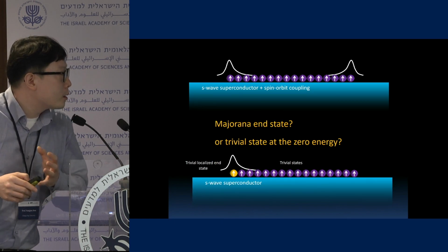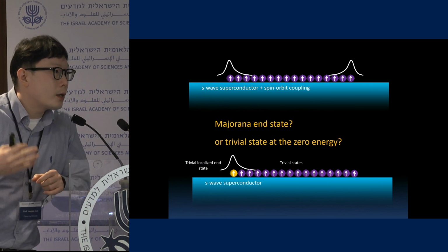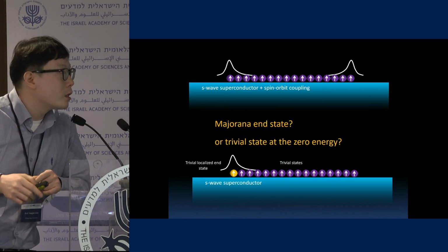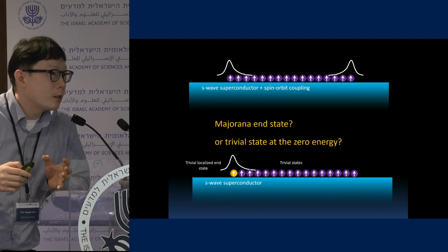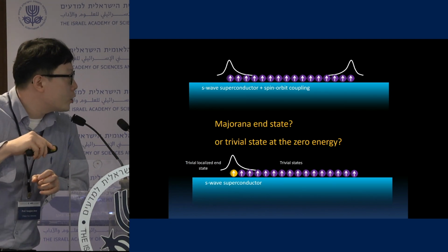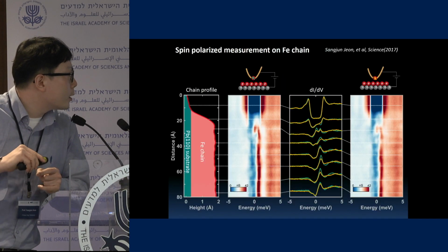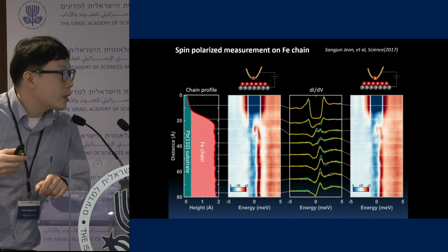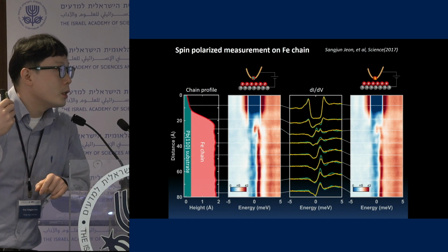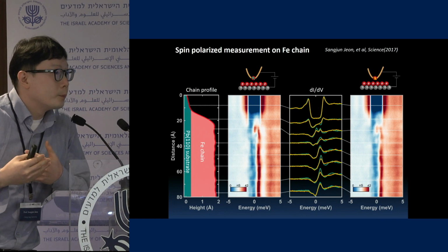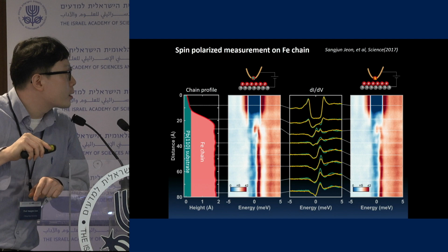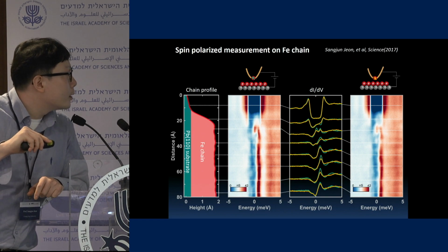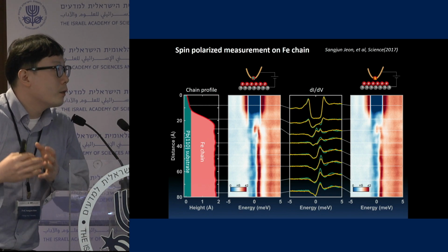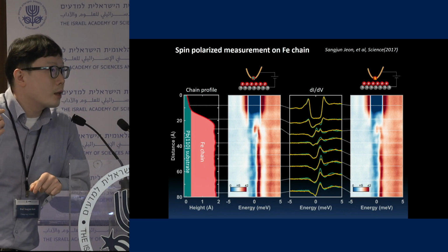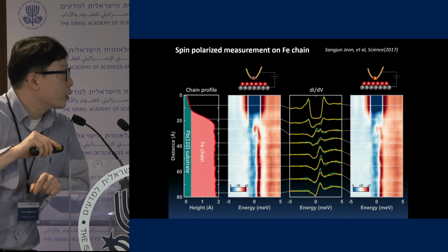And still, there are criticisms. So what we collected so far is the experimental evidence, but it is some kind of supporting evidence. But what is really actual direct evidence of the Majorana zero modes to get to understand this picture? So we use spin polarized STM measurements, and as you see here, in our understanding, zero energy state doesn't have the spin polarization because it is cancelled out by the background. That is our understanding. But somehow, if you use the spin polarized STM by flipping the spin up and down, measure the same wire, exactly the same wire, and you see the end state, zero energy end state has some strong spin polarization. This is very unexpected result, and then we think this can be understood as something related to topologically non-trivial character of these zero end states.